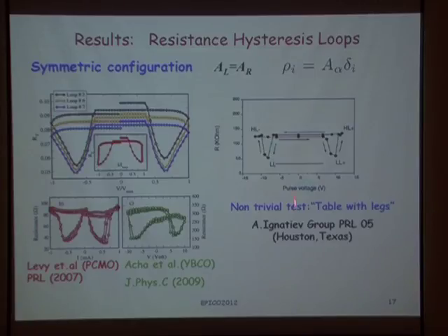These are our model simulation results, as a function of different cycling voltages applied. We start from 0 voltage and plot the resistance as a function of the voltage. We perform one loop, second loop, third loop, and here are the 5th, 6th, and 7th. Okay, so this is the result.